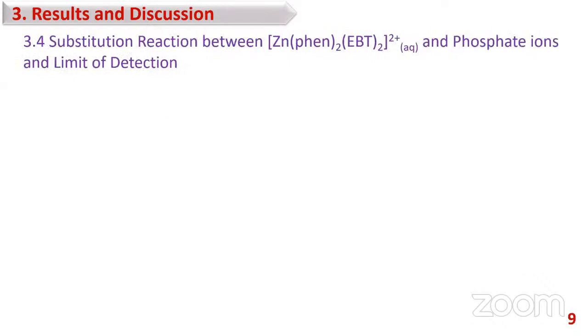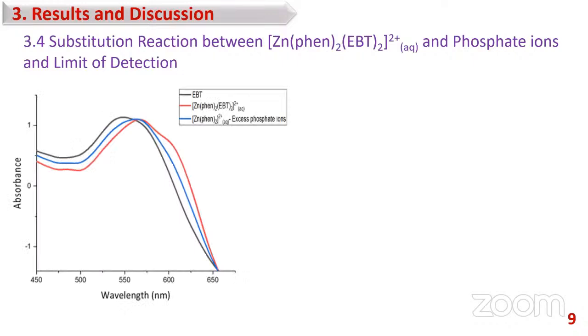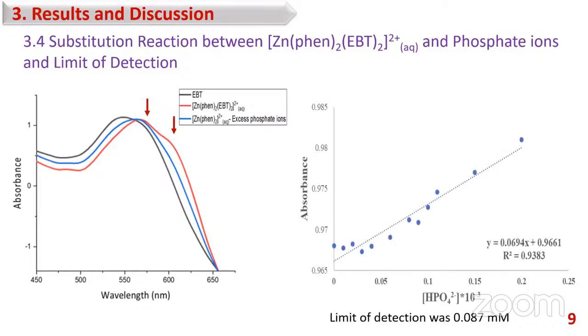Let's turn to the next slide to show the substitution reaction between zinc phenanthroline EBT complex and phosphate ions through the spectral changes. Here, the band maxima of EBT was redshifted to 565 nanometer and a new band appeared at 600 nanometer, which correlate the binding of zinc phenanthroline to EBT. Those two new bands disappeared gradually upon the introduction of the phosphate ions into the zinc phenanthroline EBT sensor solution. It clearly shows that EBT was displaced from the zinc phenanthroline complex by the phosphate ions. In addition to that, the obtained limit of detection from this absorbance plot was 0.087 millimolarity. It is an important performance parameter in method validation.